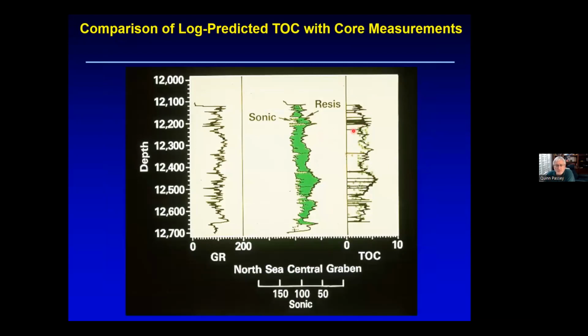This was a case also from the North Sea, and they took a core, and the geochemists didn't really like this logging approach. So they took many core samples per foot. And when we plotted it, we see, well, it agrees pretty well. The core plugs, which are 1 inch in diameter, clearly have higher resolution than the logs. The logs' combined resolution is probably 2 to 3 feet. But overall, you can identify the interval.